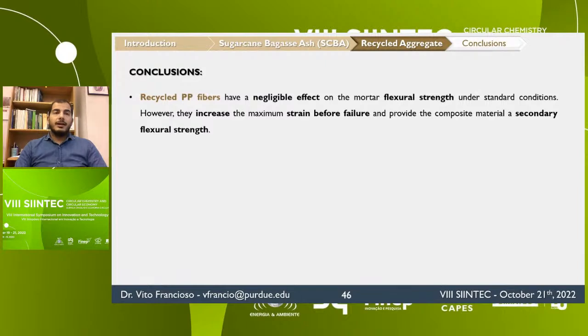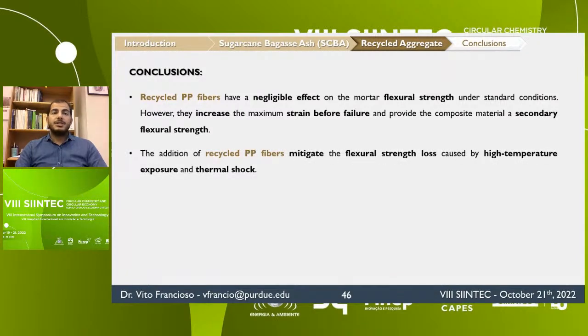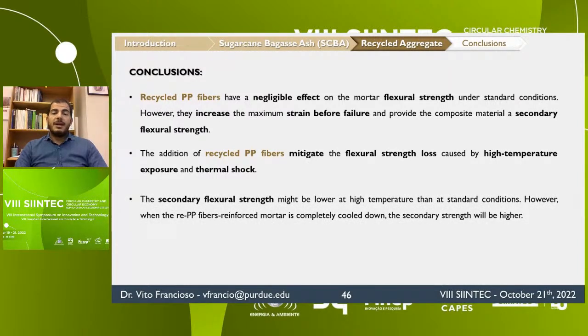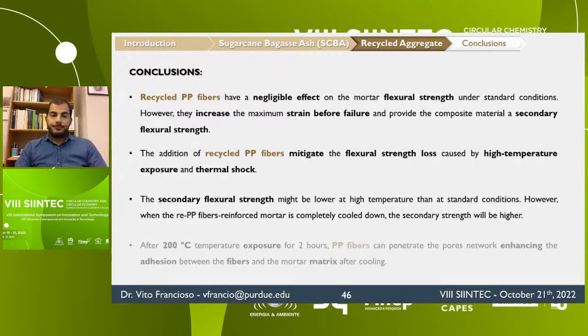So we can then conclude that the recycled polypropylene fibers have a negligible effect on the mortar flexural strength under standard conditions. However, they increase the maximum strain before failure and provide the composite material a secondary flexural strength. The addition of recycled polypropylene fibers mitigates the flexural strength loss caused by high temperature exposure and thermal shock. The secondary flexural strength might be lower at high temperature than at standard condition. However, when the recycled polypropylene fibers reinforced mortar is completely cooled down, the secondary strength will be higher. And finally, after 200 degrees Celsius temperature exposure for 2 hours, the polypropylene fibers can penetrate the pore network, enhancing the adhesion between the fibers and the mortar matrix after they are cooled down.